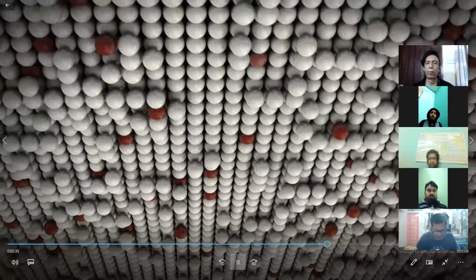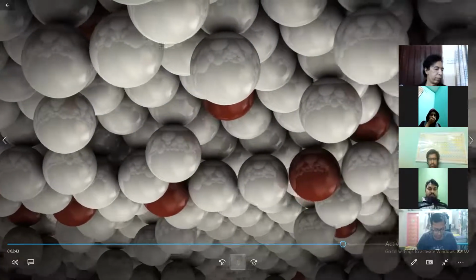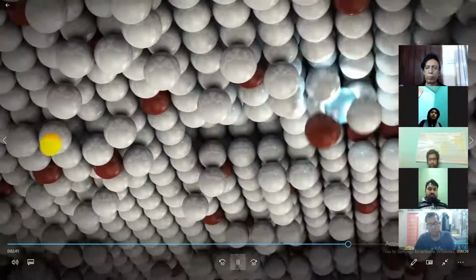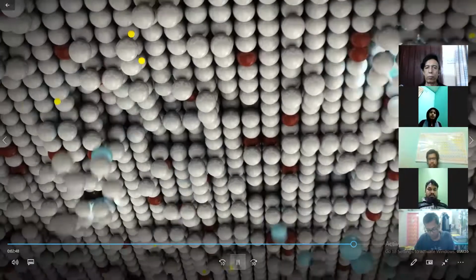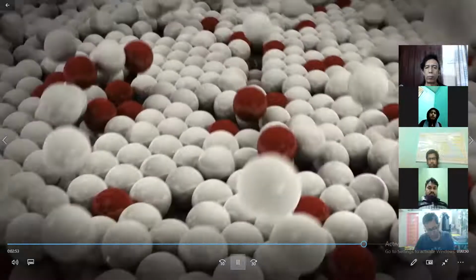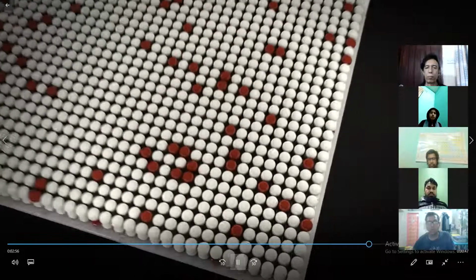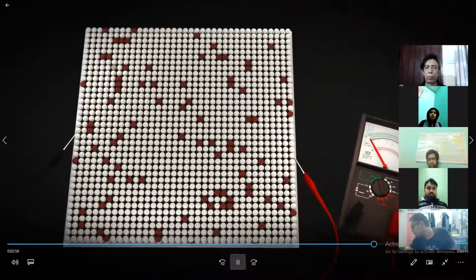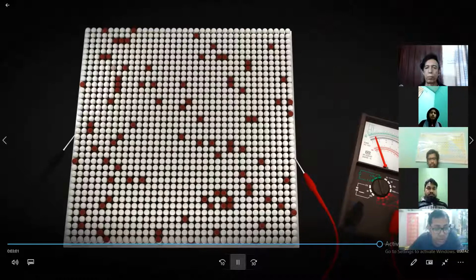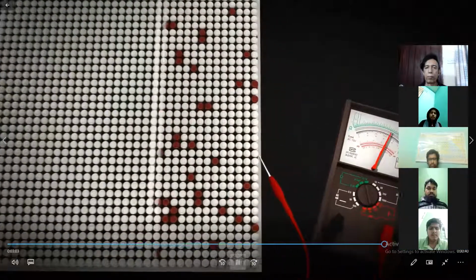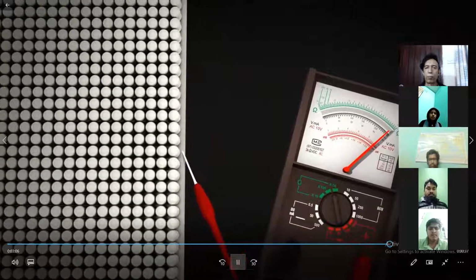But let's go back to the target material. No metal can be made 100% pure. Iron or chromium impurities in molybdenum targets are critical. Why is that? Argon ions don't distinguish between molybdenum and impurities. Impurities will also be sputtered and incorporated into the thin film. Nobody wants that. Impurities can negatively influence the thin film properties, the electrical conductivity, for example. Only highly pure sputtering targets can ensure high-quality thin films.